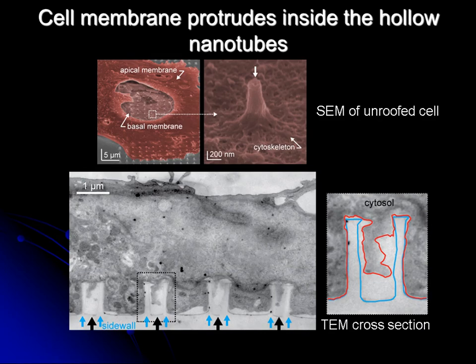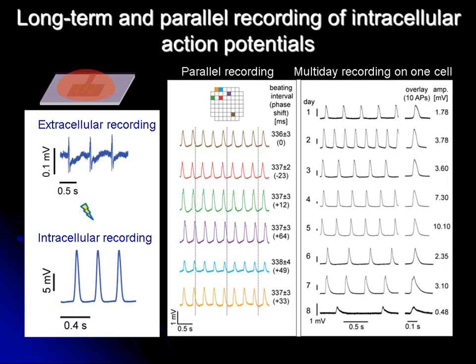So we use scanning electron microscope and transmission electron microscope to show that indeed the membrane can grow into the center of the hollow tube. In the top images, we use the unroofed cell to look at how the bottom cell membrane interacts with the nanotube. The white arrow, you can see that the cytoskeleton can actually grow into the hollow center of the nanotube. From the TEM image, it's much more clear. On the bottom of the TEM image, there are four nanotubes, and one of them is enlarged. What you can see is the cell membrane not only wraps around the outside of the nanotube, but also grows inside the nanotube.